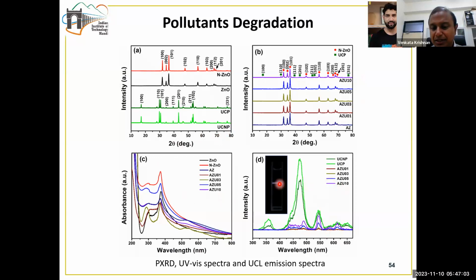And the upconversion luminescence, you can clearly see that when this material is dispersed in water and taken in a cuvette, when we shine the infrared laser, wherever the laser is impinging on this material, you can see this blue colored streak, which indicates that the upconversion nanoparticles are present because it's getting converted. The NIR light, we cannot see it with our eyes. And when it passes through this material, it gets converted to the blue light, which can be seen very clearly, visibly as well. And the upconversion luminescence spectra can also be recorded using the instrument.